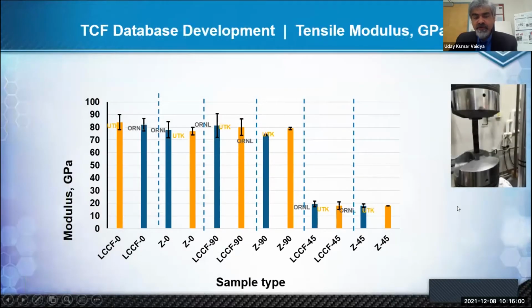So I'm giving you tons of data, but I'm just giving you one or two snapshots here. If you look at the modulus, every single composite produced by vacuum infusion and by compression molding was tested independently at two labs, at UT and Oak Ridge, without communication between the labs, so as to get fully non-biased data. I'll just point you to this one histogram here. The orange is the UT data, the Oak Ridge data is in blue.